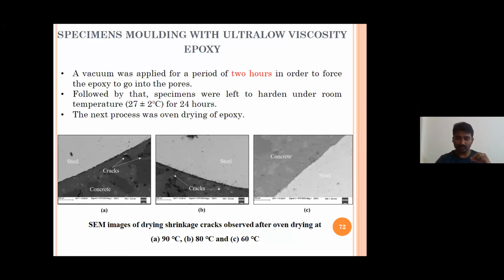If you put it on the top, then it goes inside the pores, and I have to dry it afterwards. So drying temperatures we have selected as 90 degree, 80 degree, and 60 degree. At 90 degree, there are a few cracks that we could observe. These are called shrinkage cracks. Even for 80 degrees, a few cracks are observed. At 60 degrees Celsius, there were no visible shrinkage cracks, even at magnifications of 500x or 250x. So from this, we concluded that the epoxy drying temperature should be only 60 degrees Celsius. If you increase it more and more, you observe some drying shrinkage cracks.